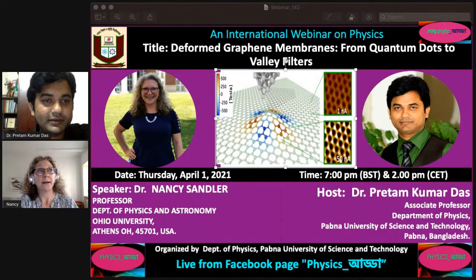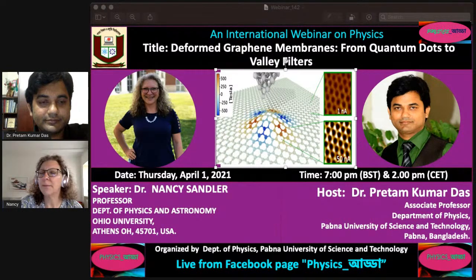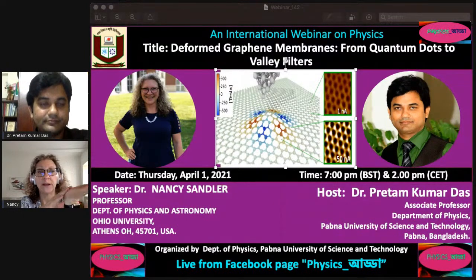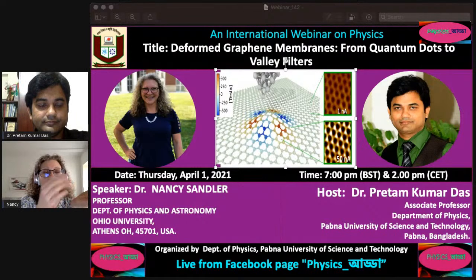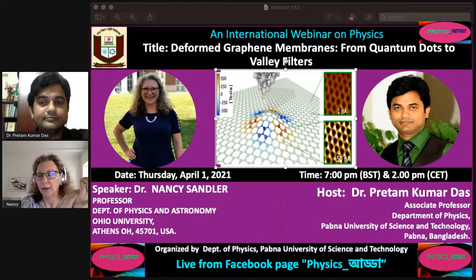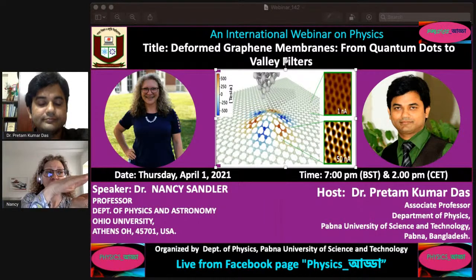Originally, people had been trying to isolate graphene for many years. The ones who were successful were putting graphite on a Scotch tape and closing the Scotch tape, and probably you're familiar. There are a lot of YouTube videos about this procedure online. The idea is that graphite is made out of these graphene layers that are very loosely attached, because the bond between the layers is a van der Waals bond, which is weak. So it's very easy to separate them. By gluing and ungluing the Scotch tapes, they were able to separate a piece of graphene.